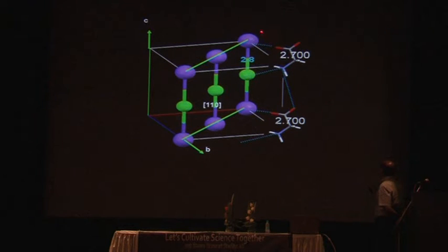And this is sodium, and this is carboxyl, so they can interact in this fashion. In this direction, if you look at the 1,1,0 plane, it is alternately sodium and chlorine. And therefore we thought probably this is the way glycine binds to the 1,1,0 face, and therefore does not allow that face to grow faster than 1,0,0.